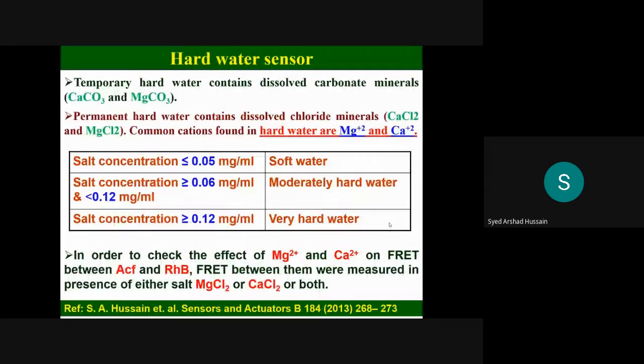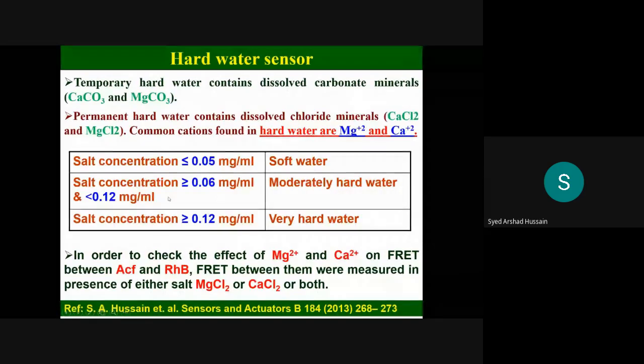Based on this, using these two molecules, we designed several sensors. For example, hard water sensors. Hard water is actually based on the presence of some cations in your water, magnesium, calcium, etc. And there is some standard definition. If your concentration is less than this, we say soft water. In between this, we say it's moderately hard water. Higher than this, we say very hard water. So what we did, we studied the energy transfer between these two molecules in the presence of different concentrations of these two cations. And we calibrated.